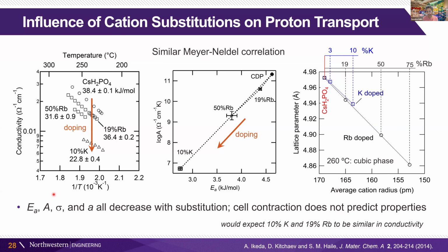And you might ask, can this be correlated in some way to the crystallography of the materials, to the crystal chemistry? Because, of course, as you introduce these smaller dopants, the lattice constant decreases. And we cannot attribute it directly to an overall change in the unit cell volume. The unit cell volumes between the 10% potassium doped and the 19% rubidium doped are similar. You can see that on the right side plot. Yet the difference in conductivity is quite significant. So it can't be just explained by the change in cell parameters. And we would have expected, for example, the 50% rubidium to be significantly worse than the 10% potassium, if it were all just about the macroscopic change in the unit cell, whereas the 50% rubidium is substantially more conductive than the 10% potassium.